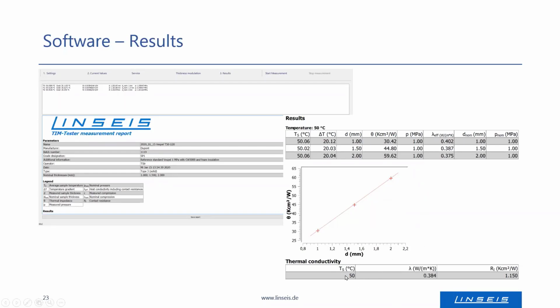In the end, the end results are shown: the average sample temperature, the thermal conductivity determined as the inverse of the slope from this line, and the contact resistance, which corresponds to the offset in this graph.